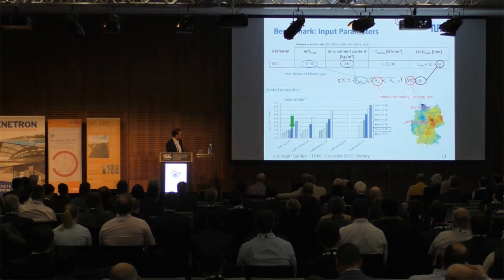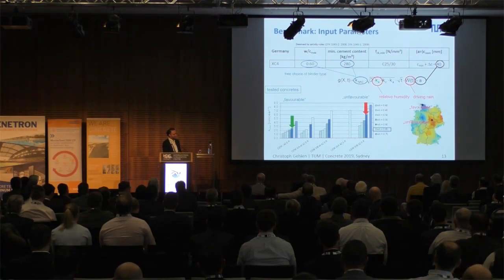In this aspect, we had a maximum water cement ratio of 0.6. And this is a favorable, very carbonation resistant concrete, which is a CEM I OPC. And the second one, which is unfavorable, was a CEM III/B, which is a blast furnace slag cement. So Hamburg is a very wet spot, and Halle, as you can see here, is a very dry spot. And we combined these combinations and collected all the data which is necessary to run the calculation.